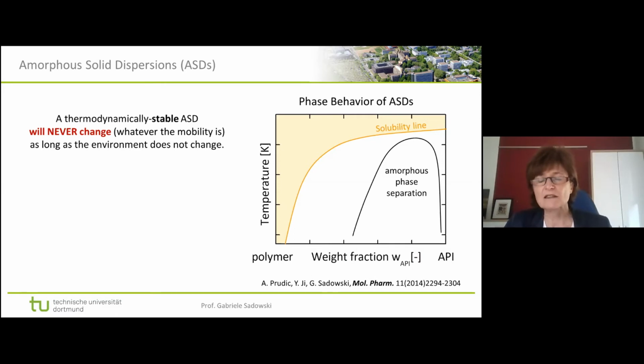And when we started this research, as a patient, I was of course hoping and also assuming that all the ASDs on the market would be somewhere here. What we really found is that you are usually at low temperatures. So this is the melting point of the API, and it is usually very high. So storage temperature or room temperature is somewhere down here. So this is the temperature range we are usually interested in. And then we have investigated several ASDs on the market, and we have found them here or there. So actually the bad news is none of the formulations we have investigated so far is stable.